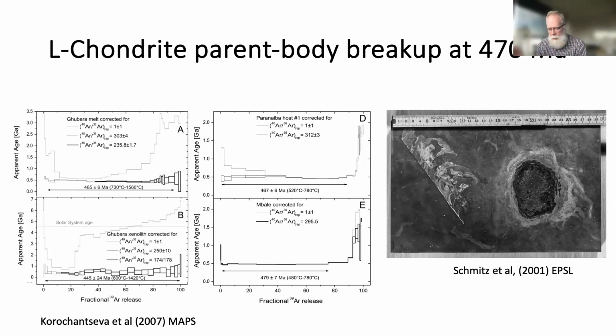So the main way that people do Argon-Argon dating is step heating. In step heating, you take a piece of sample, you heat it, and run the gases in a mass spec and measure your argon isotopes. And you do incremental heating. You gradually do this step heating and measure as you go. If you get a plateau in age as you heat, that plateau then gives you an age.